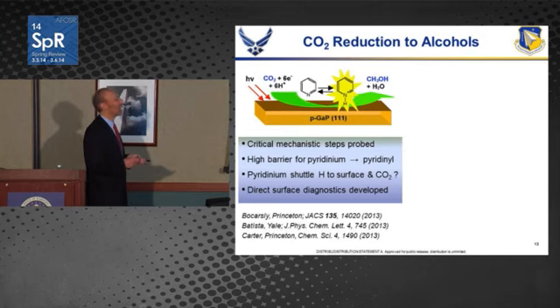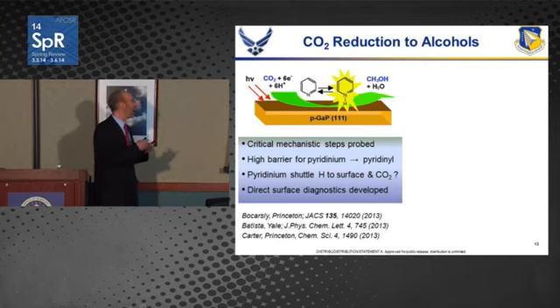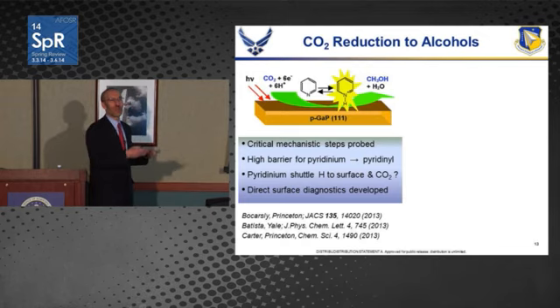So within this MURI effort, Emily Carter and her colleague, particularly a postdoc named John Keith, who's now at University of Pittsburgh, did a study of what was the mechanism of this process, and they found that one of the first steps of this process that was originally proposed, pyridinium going to a pyridinyl radical, was really energetically unfeasible. That couldn't be the process because there was much too high of an energy barrier. They did a very detailed study on this.